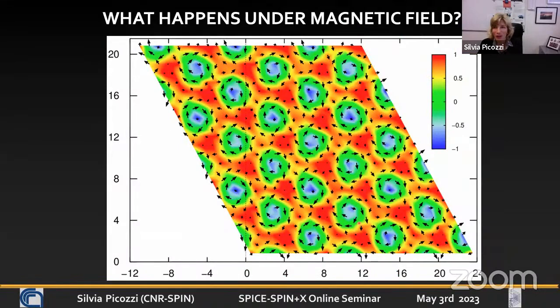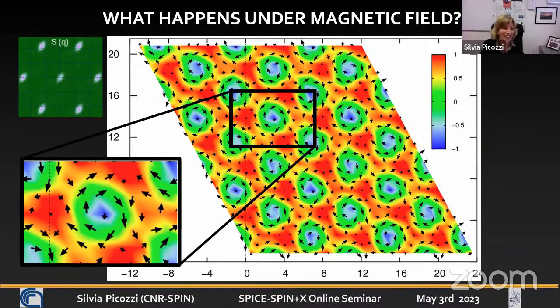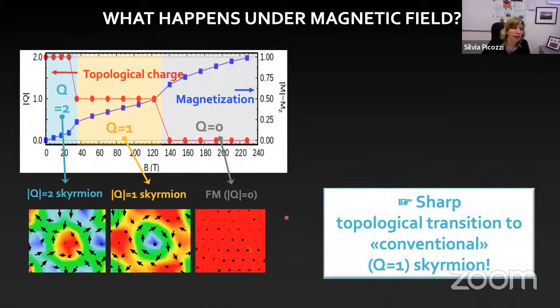And so we also thought it's interesting to look at what happens under a magnetic field, because usually the skyrmion pops up with magnetic field. And what happens in our case is that this anti-skyrmion disappears and evolves into a standard skyrmion, with topological charge equal to 1. So if you don't have any magnetic field, you have topological charge equal to 2, then there is a sharp transition to the state Q equal 1. And then if you apply a really large field, okay, here you shouldn't look at the quantitative Tesla values, it's probably far off from reality because of the computational parameters, but the sequence of transitions should be correct. So we start from Q equal 2, then jump to Q equal 1, then jump to the ferromagnetic state.